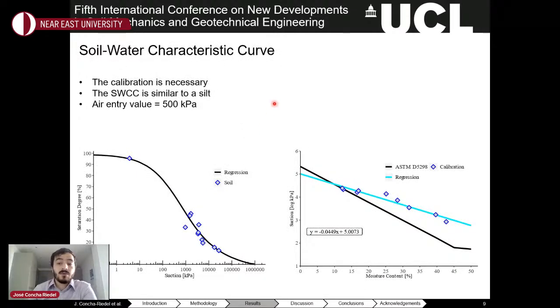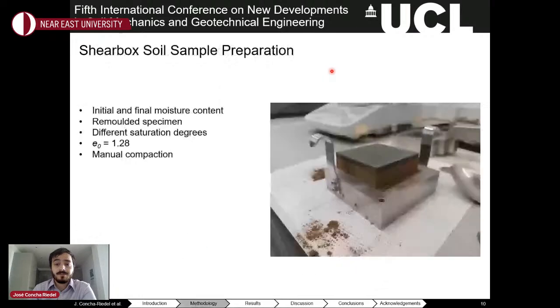The soil water characteristic curve was obtained using the filter paper technique. A special emphasis was put on the drier part of the curve, as adobe blocks have low moisture contents. The filter paper was calibrated using different concentrations of sodium chloride solutions, and the results showed a curve different to the one proposed by the ASTM standard. From the curve, it can be seen that the soil has a high air entry value and that its shape resembles the shape of a silt. This corroborates that the soil is not a sand, as sands do not have such high air entry values.